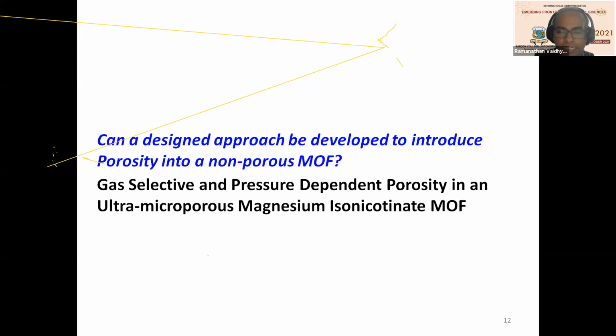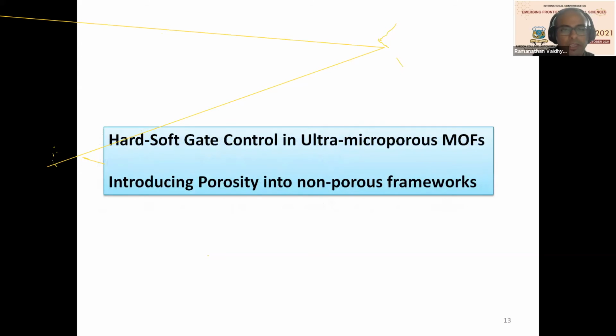Typically, all this flexibility and dynamicity that I showed you will be associated with a MOF which has long or flexible linkers, okay? Because these are required to make the MOF act like a sponge. But we are trying to see, can we come up with a method where even in a MOF made of a very short linker, the linker in our case being isonicotinate, which is 4-pyridine carboxylic acid, okay? That is a very short linker compared to some of the linkers which are already reported. Can we introduce openness into this type of MOF? What kind of chemistry can we do? The chemistry we are going to do is what is called a hard-soft gate control to introduce porosity into otherwise non-porous ultra-microporous MOFs, okay?